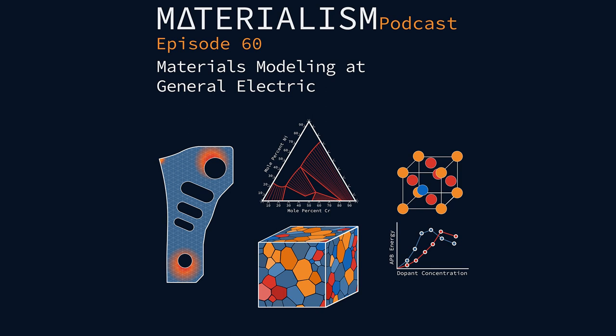And what's great about that is now that you can do that, you can measure locally what the composition is. And then using a simulation technique, like we've been discussing, something like CALPHAD, you can say, okay, at this composition, what should be the molar volume? And then you can compare that to the region next to it, which has a different composition, and calculate the molar volume of that region. And if they're different, then you can say, well, that's our driving force for crack formation, because there's a difference in here, and that's what's causing these cracks to form in some materials, but not in others.